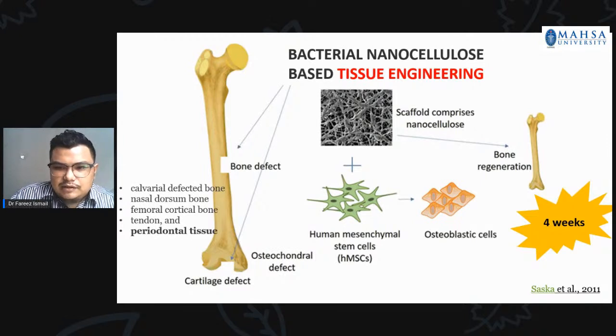And there's an evaluation of this non-critical bone defect in the rat tibia with the BNC membrane, which then showed no inflammatory action with defects, while the defects were completely filled by the new bone tissue after only 4 weeks. And similar result was also obtained from another study using a rat skull, and they show a new bone formation on the marginal center of the bone after 8 weeks of the implant.